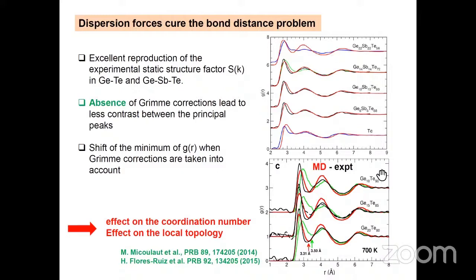And here's another example, again in the liquid, but on binary GeTe, where now I have represented the red curve, which is the MD simulation. The black curve is the experiment performed in Grenoble. And the green curve is exactly the same simulation, but without the Grimme correction. And now you clearly see the shift to the right, to larger distances, of these poor or spurious simulations with respect to the curve in red. So clearly there will be an effect on the coordination number, because the integration of those peaks gives you the coordination number, and of course an effect on the local topology.